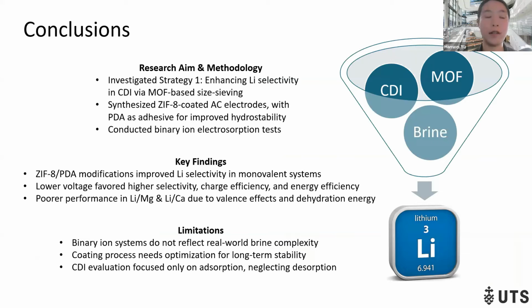Here is a brief conclusion of this part of the research work. In this research, I investigated strategy 1, that is enhancing lithium selectivity in CDI via MOF-based size-sieving. I synthesized the MOF-based AC electrodes and used PDA as an adhesive for improved hydrostability, and conducted a CDI test using binary solutions. The key findings include that the ZIF8 and ZIF8 PDA modification improved the lithium selectivity in monovalent systems. Lower voltage favors high selectivity, charge efficiency, and energy normalized to lithium. The poor performance in lithium-magnesium and lithium-calcium is due to the valence effects and dehydration energy.